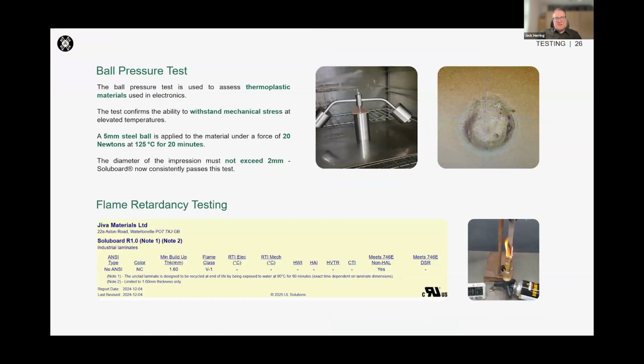So this test at the top, the ball pressure test, is something which not everyone is familiar with in a laminate world. Because we're a thermoplastic, this is a unique test which is used for thermoplastic materials used in electronics. It took us a very long time to pass this test because there's a 5 millimeter steel ball which is applied under a force of 20 newtons at 125 degrees Celsius for 20 minutes. This is quite a strong force at quite a high temperature for a thermoplastic material.